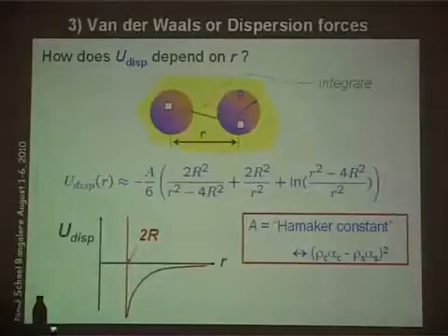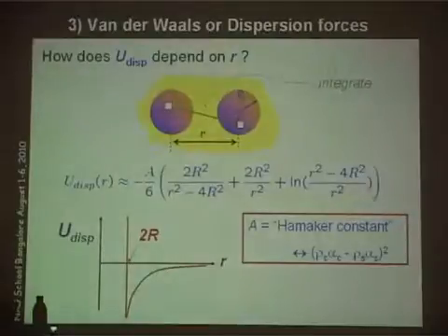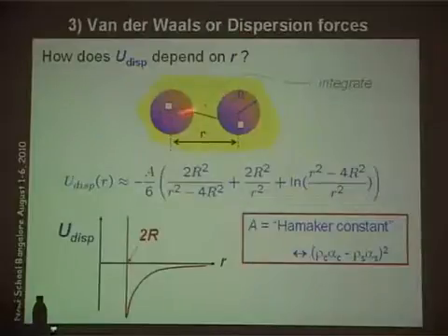Of course, there were people like, I think, was it Lifshitz and London? Yeah, and many other people who did those calculations. It is only an approximation because it takes only two-body, pairwise interactions into account. It does not take higher order interactions into account. But for short distances, you obtain for two spheres a much more complex scaling of the van der Waals as a function of the separation between them. And you see it's no longer just a scaling law 1 over r to the power 6, but it can change depending on the shape of your particle.